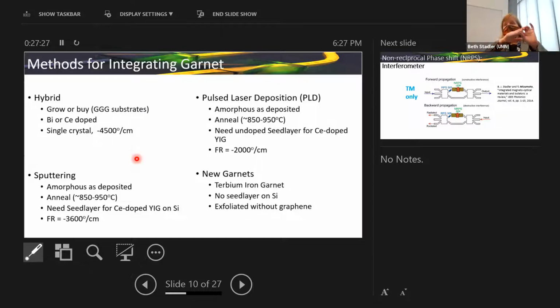All right, then you have to rinse the resist because you're going to anneal it at 900. Then you have to repattern your resist, put down your doped cerium or bismuth yttrium iron garnet. Now you get maybe even as much as minus 4,500, maybe minus 3,600, maybe minus 2,000, but still at least 10 orders of magnitude better than undoped YIG.